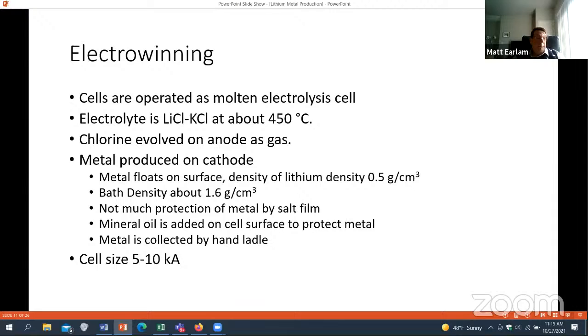So let's look at electrowinning. There is one plant in the United States that does electrowinning. It's in North Carolina. They use a potassium chloride, lithium chloride bath because lithium chloride is very hygroscopic and is a pretty high melter. Lithium metal melts at about 180 centigrade, so you don't really want to run a cell that's too hot, because in all these electrolytic processes, the further away you are from the melting point of the metal you're interested in, the less likely you have very good current yield, because you have higher solubilities of chlorine in the electrolyte, which causes recombination, and then that causes the current yield to go down.